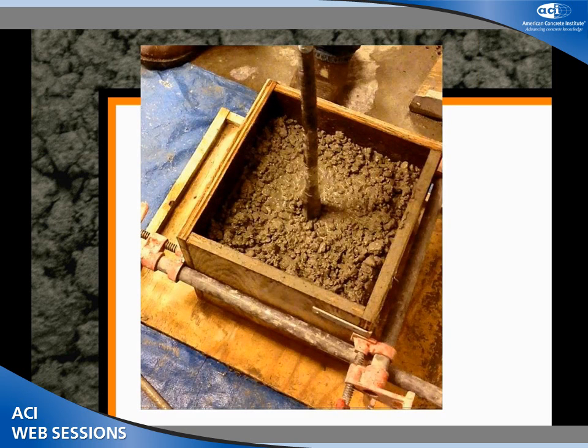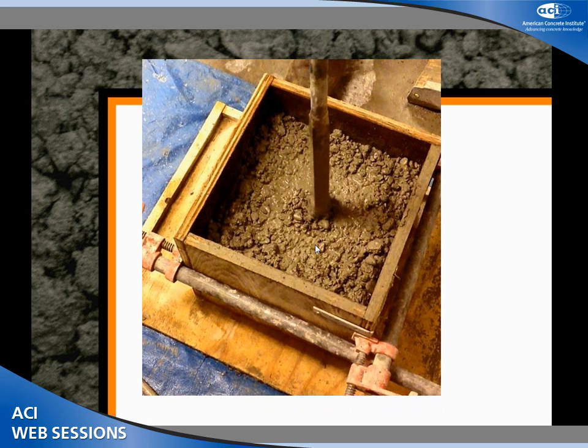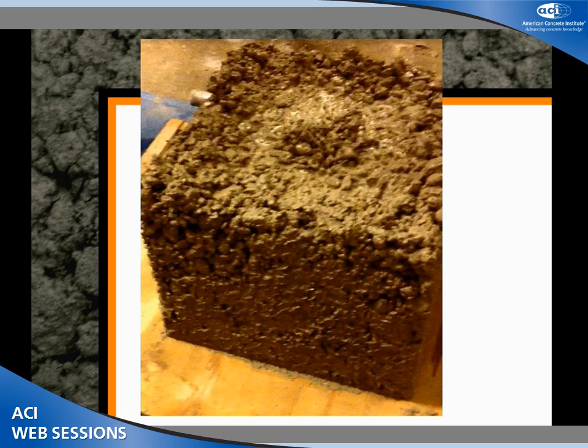That's what the test looks like at the beginning. There's the vibrator hovering above, then it comes down and starts to consolidate the concrete. You can see there's something called a sphere of influence — our concrete nerds would say we've exceeded the plastic yield stress of that concrete. Then as we start to pull the vibrator out, we can see this sphere of influence — this area of vibration — did not make it to the walls. It's stuck in the middle. That's not good.